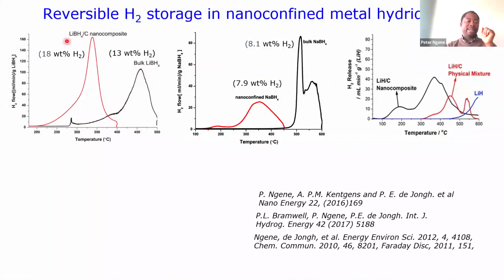But if you put this inside the carbon, if you nanostructure it and confine it in this carbon, what you see is that already at a much lower temperature, you can release the hydrogen. And then we have a much higher amount of hydrogen compared even to the bulk. But we're going to come back to this. The same thing we see for sodium borohydride, which by the way has a very large amount of hydrogen. You can see the same thing here.